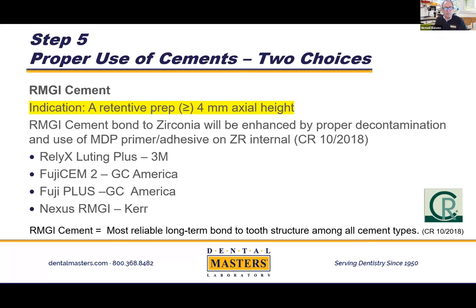Step number five is the proper use of cement. We, in essence, have two choices here. We have the resin modified glass ionomers. The indication is a retentive prep that is greater than or equal to 4 millimeters in axial height. The RMGI cement bond to zirconia is enhanced by two things, by proper decontamination following try-in and the use of an MDP primer/adhesive on the internal. That's noted in CR in October of 2018.